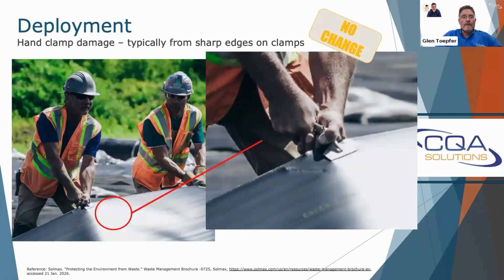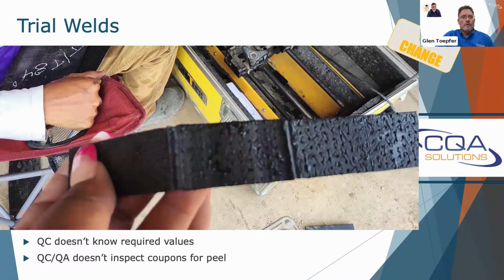Deployment, hand clamp damage. This is an image I took from a manufacturer last year. It's still there as of yesterday, and I use it to point out, I don't think manufacturers should be promoting bad quality, but yet they are. You can see here, they're doing their hand clamp, and here's damage shown right there. That happens all the time in the field because these hand clamps aren't rounded. We continue to see that as a big issue, and they result in failed seams and things that go undetected.